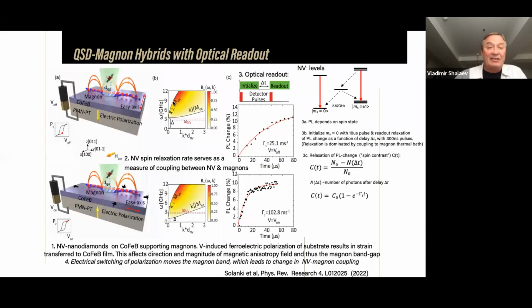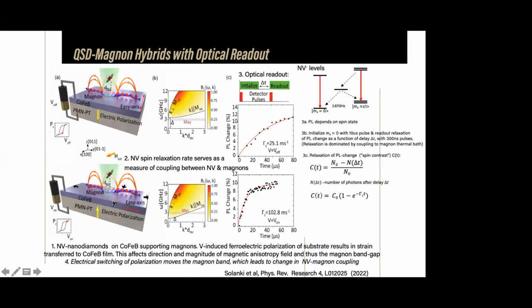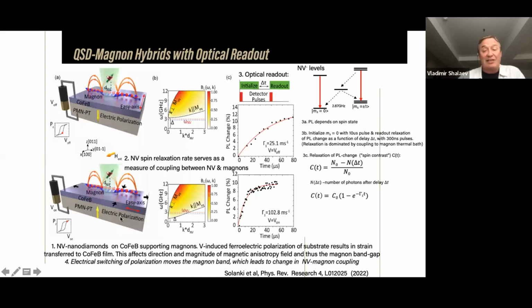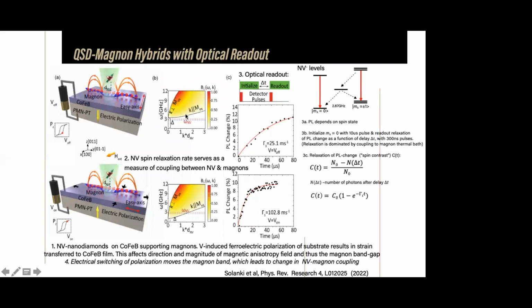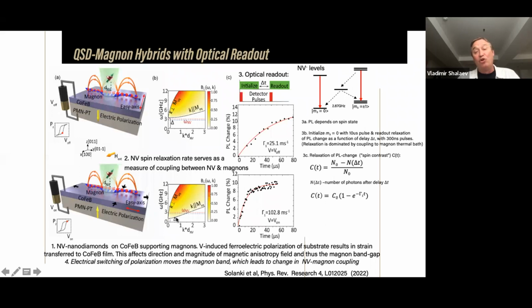This is a little bit busy slide, but the idea is actually simple. You have this magnetic film, CoFeB, on top of this ferroelectric substrate. And you have a nitrogen vacancy spin on top of this magnetic film. So when you apply voltage, you create stress in your ferroelectric substrate. This stress is converted to a change in magnetization of the magnetic film. And when you apply voltage and change the magnetization, as a result, the magnon band as a whole moves.